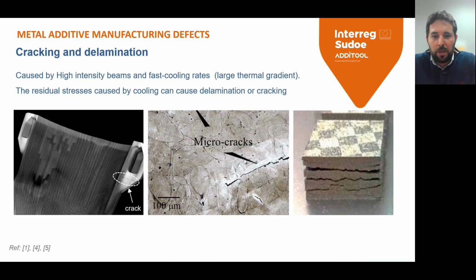Other typical defects presented in additive manufacturing are cracking and delamination. These anomalies could be caused by high energy density and fast cooling rates. These thermal gradients cause residual stress, and that could finally induce cracks and delamination. You can see here a computer tomography cross-section with a crack, some micrograph images with micro cracks, and some delamination that you could see at naked eye.